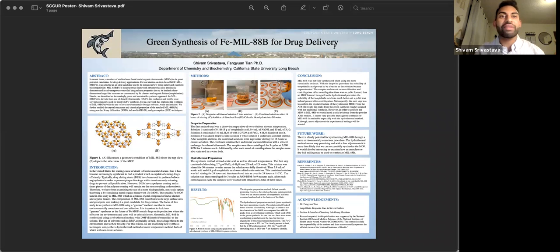Generally, we have been synthesizing MIL-88B using a solvothermal method using DMF, or dimethylformamide, as a solvent. The use of DMF, especially in bulk, poses a huge threat to our environment, especially due to the toxicity of the solvent. So for this reason, we're examining new synthesis techniques that use a hydrothermal method or a room temperature synthesis method, that both do not use toxic solvents.